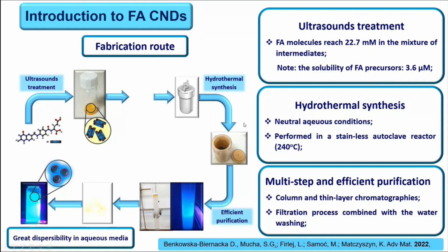And last but not least, I would like to also introduce you to the folic acid-based carbon nanodots, where our precursor is folic acid, so a highly biocompatible molecule, which under ultrasound treatment and then with the hydrothermal synthesis and purification shows a great dispersibility in the aqueous media.